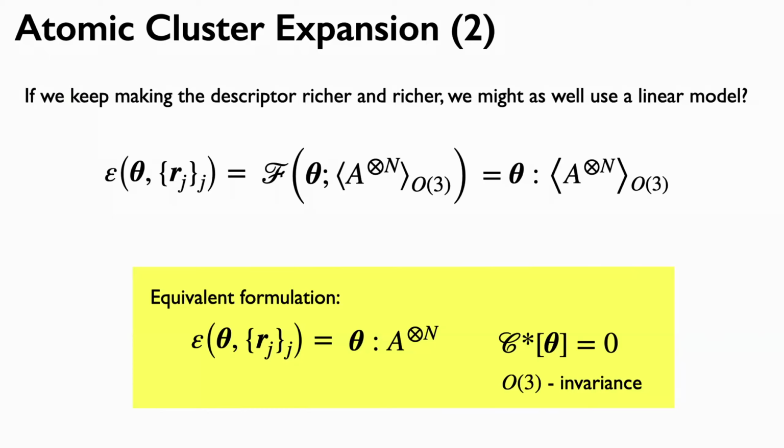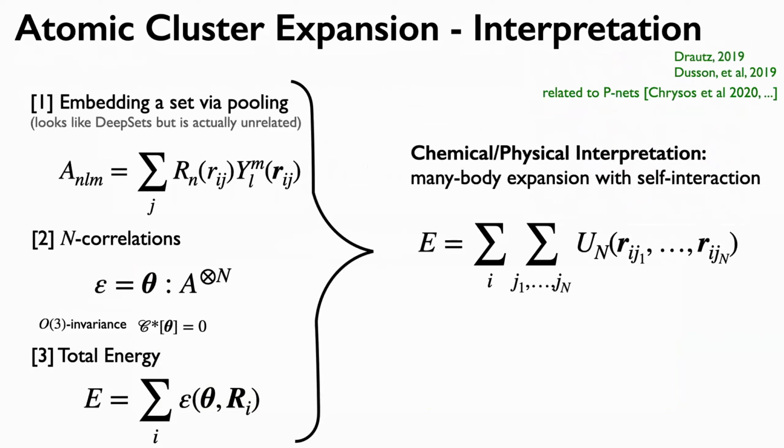I don't know what that is. I suspect there is something in here that I haven't seen. Anyways, we don't know for sure, but if we go to correlation order n, where n is the number of atoms, then we're done, for certain. I think in fact n-1 I can prove. That's helpful for proving things. But the reality is that we have yet to encounter situations where going beyond n equals 5, 6, 7 helps you in any way. More realistically, we're in the range of n equals 3 or 4.